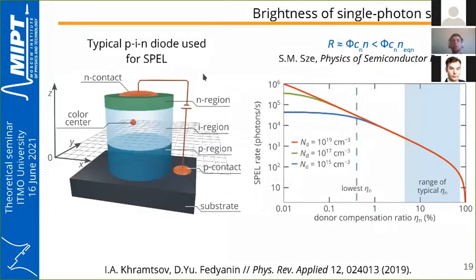If we take a typical PIN diode used for single-photon electroluminescence, we make the following assumption: since electrons are injected from the N-type layer into the I-type region where the color center is, it's obvious to assume that the density of electrons near the color center doesn't exceed the equilibrium density of electrons in the N-type layer. In this case, we can write down this inequality.